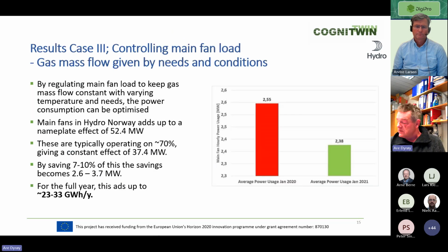And when we look at the control of the main fans, we managed to take down as much as 10% of the use by basically putting the gas flow on a constant mass flow in terms of normal cubic meter per hour. If calculating the same thing for the whole collection of main fans that we have in Hydro Norway, this would add up to 23 to 33 gigawatt hours per year in saved cost, basically by tuning down the fans during the colder part of the day and only gearing it up during the hotter period of the day.